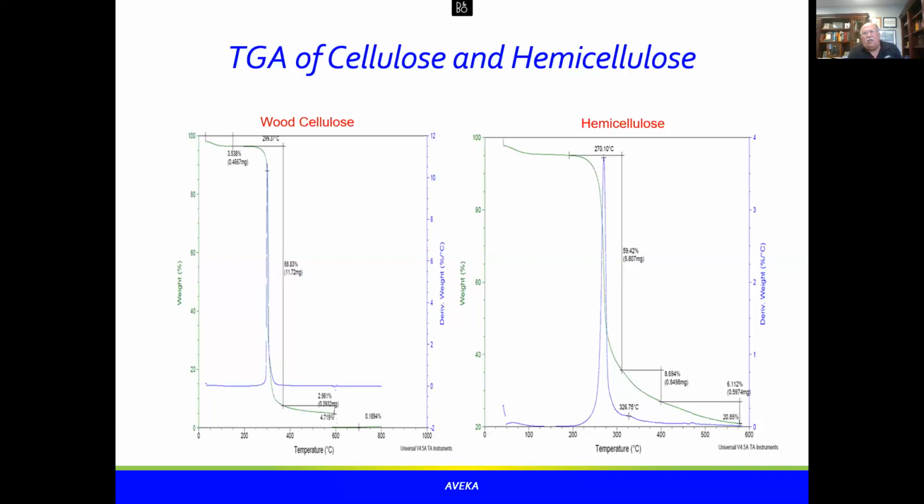Not easy. The analytical techniques for this are difficult. Usually it's a wet method for analyzing the thing. But we found in the literature that some people had talked about using TGA as a method of analyzing for cellulose and hemicellulose in mixtures. And lo and behold, we actually improved the process quite a bit. And if you do a very precise TGA, you can get a decomposition point for cellulose and hemicellulose that's different.